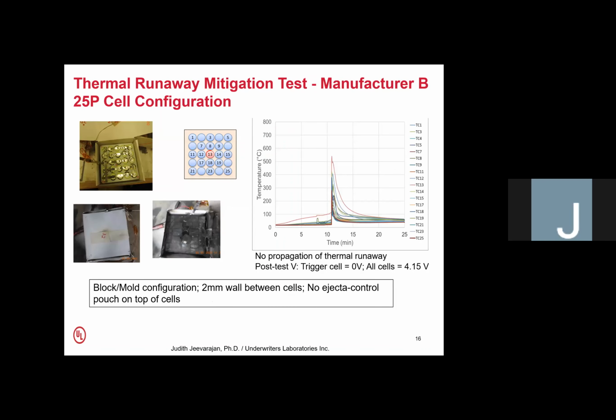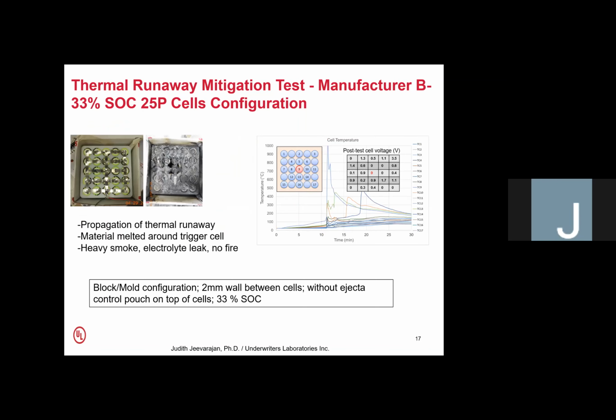So going on to the next one, same manufacturer B. What we did here is, without the pouch, we carried out the test, but with the same block mold, and we found that there was no propagation at all. And as you can see, all the cells held voltage. The next one was 33% state of charge. We found that at 100%, we do not have any propagation. So we wanted to see how 33% behaved, because in the 100% we saw that initial spark, right?